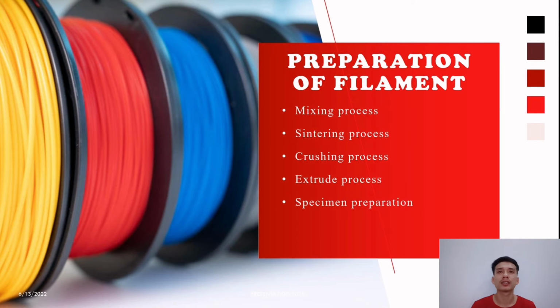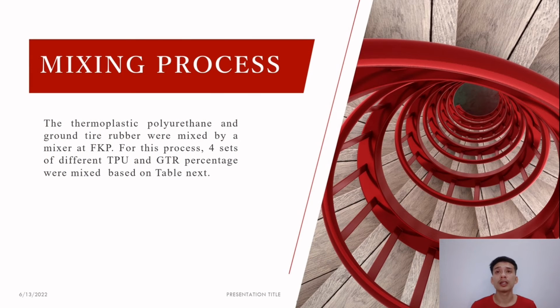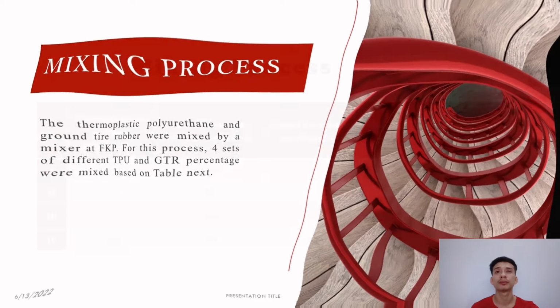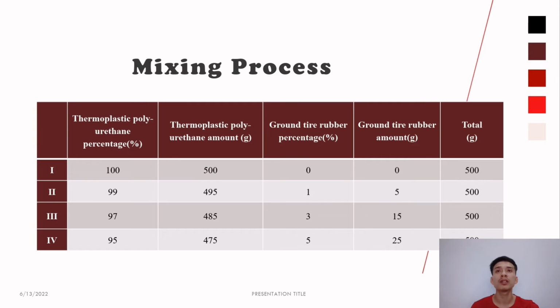After all the tests, we proceed with preparation of the filament. We will go through the mixing process, sintering process, crushing process, extrusion process, and specimen preparation. For the mixing process, the TPU and GTR were mixed by a mixer at FKP. For this process, 4 sets of different TPU and GTR percentages were mixed based on the table. This is the table for the mixing process.